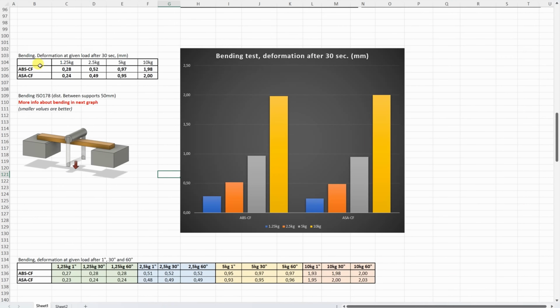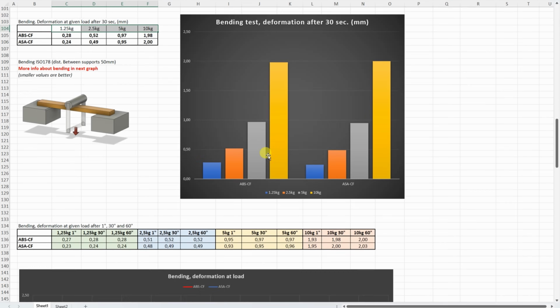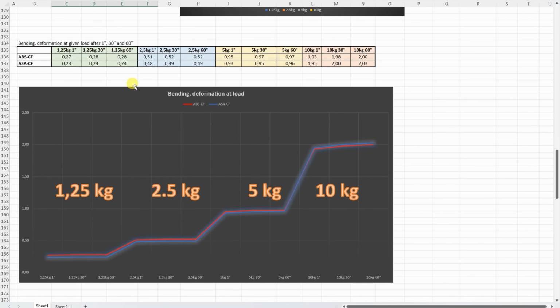On 3-point bending test, this is the deformation under these loads after 30 seconds. No big difference between these two materials, but let's analyze better this graph where we can see the deformation under these loads after 1, 30 and 60 seconds. And actually we can see that no big difference between these two materials, and they can handle quite good even this bigger load because there is no additional deformation during the time or very minimally.